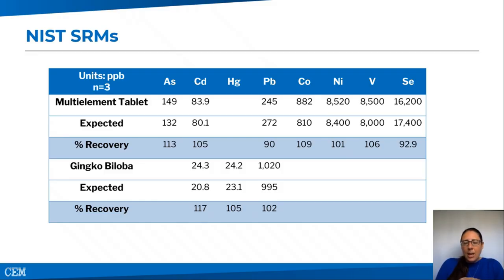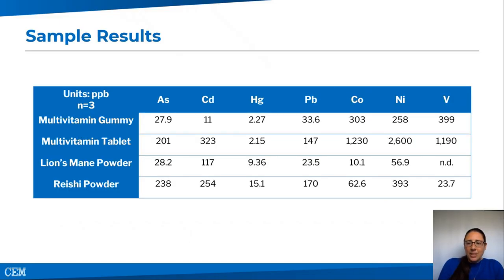You always want to focus on your big 4 heavy metals, so your arsenic, cadmium, mercury, and lead. In most cases, those are the ones that are regulated. You need to make sure that you are not above limits for those particular elements. And then we also looked at some of the other elements of interest, so your cobalt, nickel, vanadium, and selenium as well. That's specifically why we're looking at these elements, and these are the ones that were qualified for the SRMs, just to qualify that. But overall, percent recoveries look good across the board. So this really gives us the confidence that this method is fit for purpose for what we're trying to achieve. So let's look at the sample results.